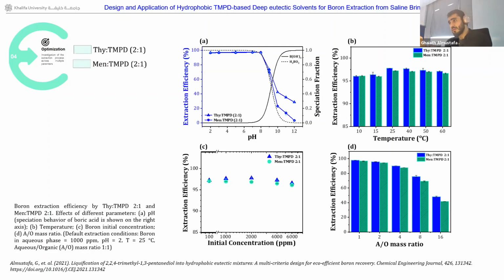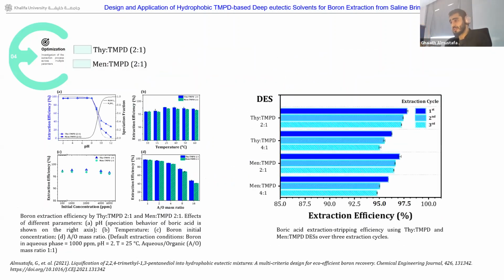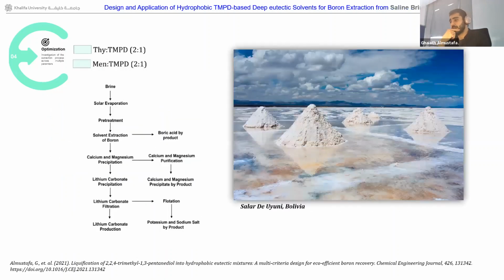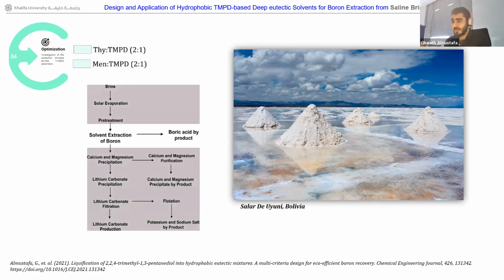But it doesn't stop there. We've also tested it over multiple extraction cycles, and we confirmed that it's stable with very minor losses over 3 cycles. And this also feeds into what kind of application that we're looking at, and that was the saline brine. And as the previous speaker said, in most lithium extraction processes, there is boron present in the feed itself, in the matrix of the solution itself. So boron extraction is usually done as a pretreatment before the lithium extraction process from saline brines.